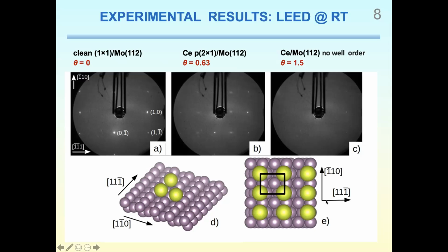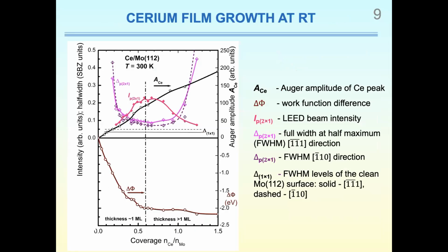Further coverage increase led to a gradual attenuation of both integer and half-integer order beams, which totally disappeared at cerium coverage about 1.5. The contact potential difference and Auger electron spectroscopy measurements indicate consistent results and complement the LEED observation. This graph shows the coverage dependence of work function difference relative to clean molybdenum surface, cerium Auger peak amplitude, and parameters of the half-integer order LEED spots, namely the intensity and full width at half maximum.